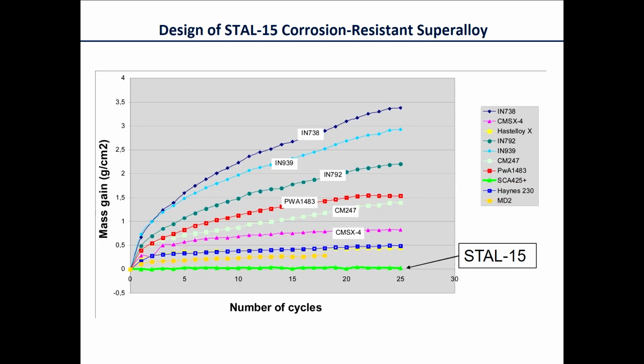databases. And you can also see here from so-called thermogravimetric oxidation tests that this new alloy, which had the code name STAL15, STAL stands for Siemens turbine alloy, has very good performance in oxidation. So under mass gain trials at temperature, you can see it has very low rate of mass gain because its oxidation reaction is very, very slow.